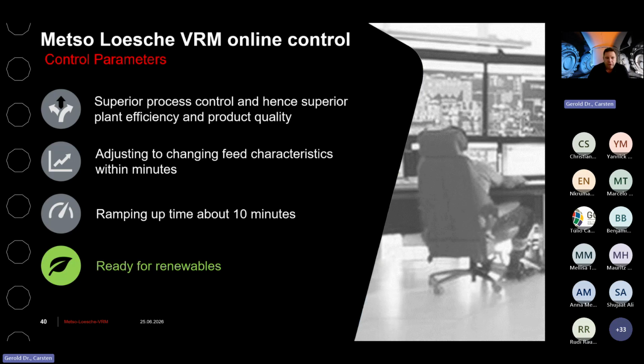In the project I reported, the West Musgrave, the 2 lines, the idea would be if the power drops too far, you just stop one of the lines, because you can shut it down and then switch it on as you like. It's not like in a wet circuit where this is very difficult because you would have to flush, and where it also takes about half a day to stabilize. So these systems are really quick and flexible.